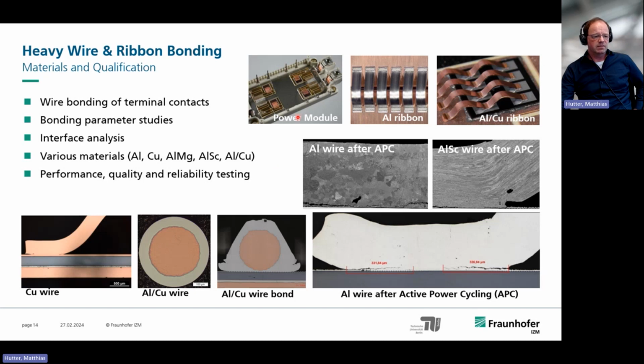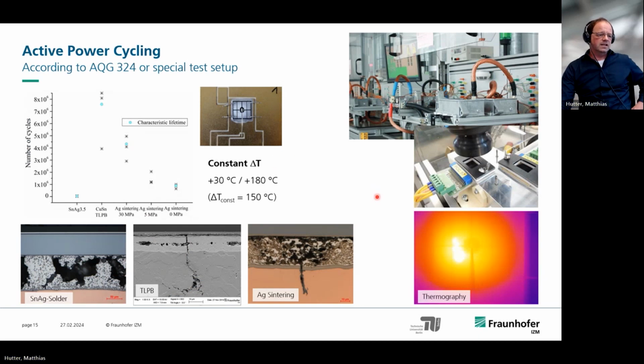Of course, we have also here ribbons in place on power modules, which are more or less state of the art. These power cycling tests can be done for whole power modules as a standard test. It can be done for ribbons or wires, as has been shown on the last slide, or we can also do it with a special focus on the die attach, as you can see here. We have here the IGBT die, which is used here as a heater, so we don't use the full current, so we use it in a state where it's normally not used.